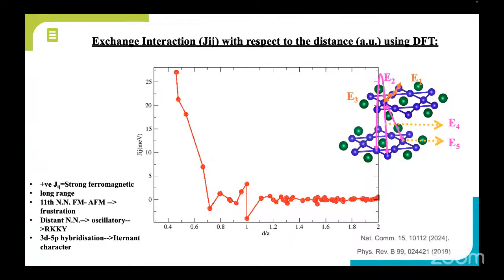That actually tells us that there might be some kind of frustration in the system, because for the same distance, one interaction wants the system to be ferromagnetically aligned, and the other tends to align it antiferromagnetically. Further analyzing the plot, we come to know that for larger distances, the system has an oscillatory kind of behavior, which is reminiscent of RKKY oscillations. And we also saw from the previous band structure plots some kind of hybridization between the d and p states, which can also help the exchange interaction.